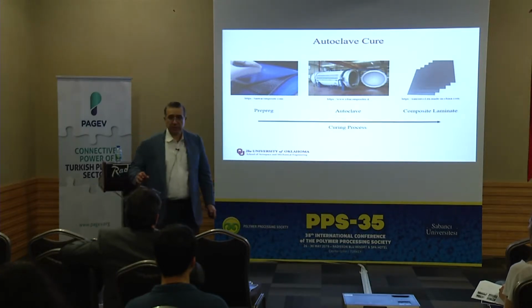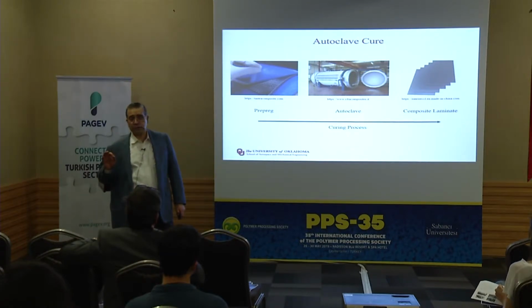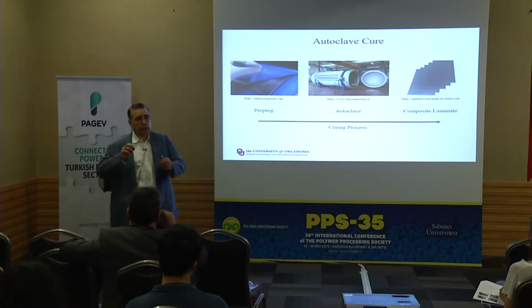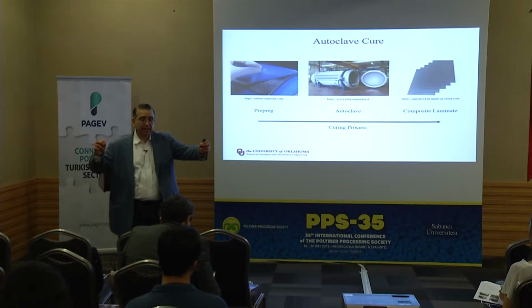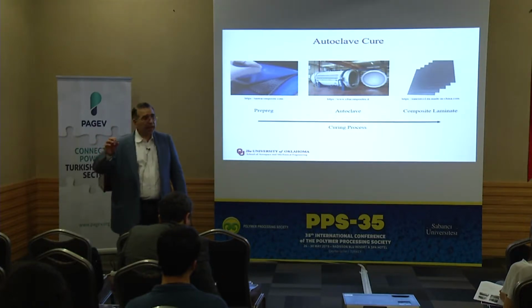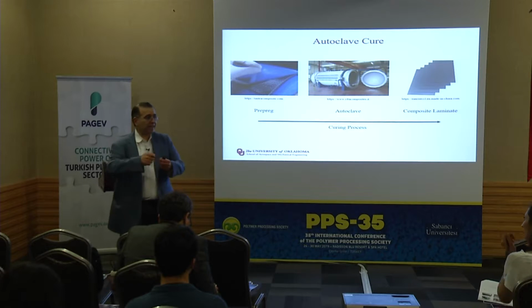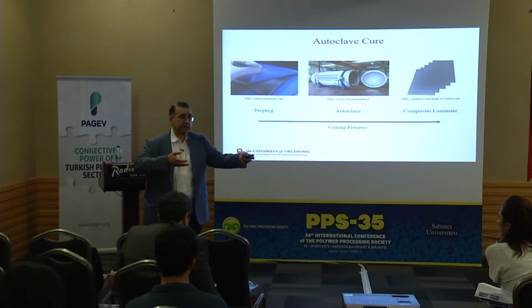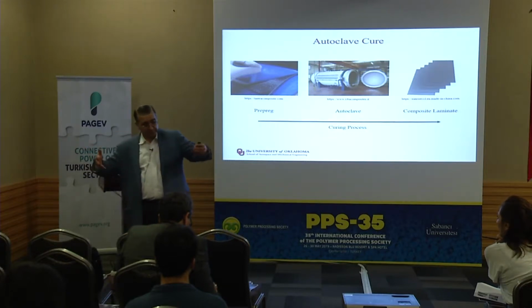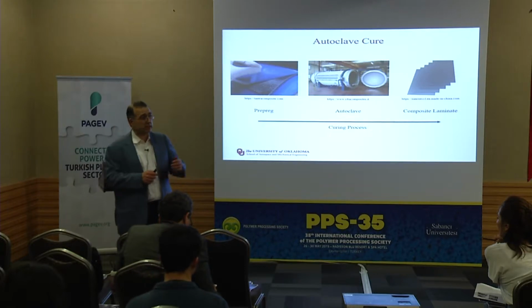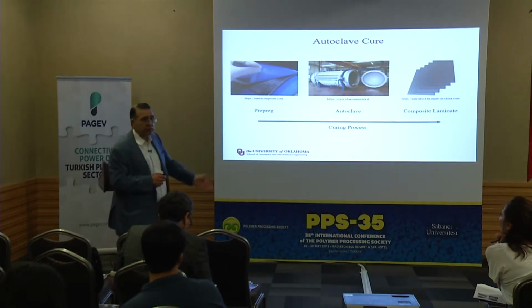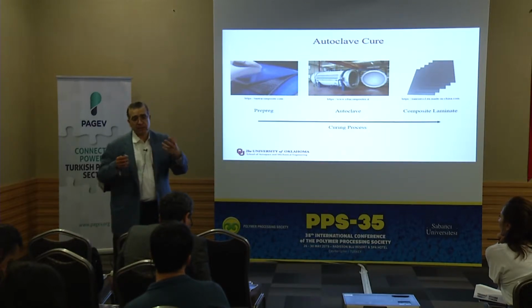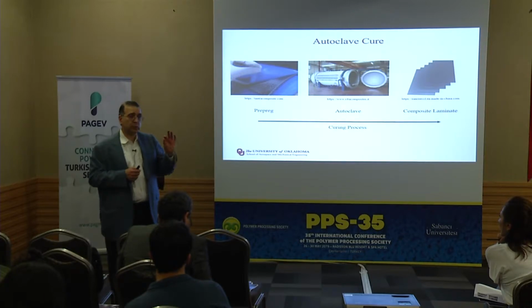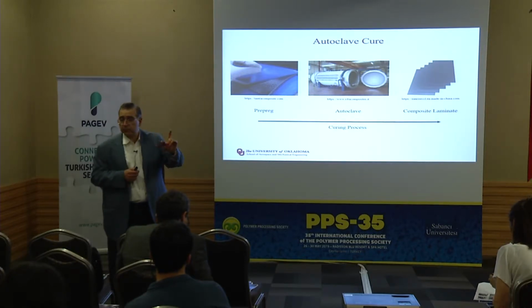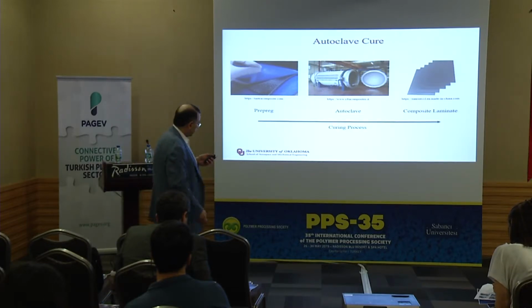If you are working with a prepreg, make sure that you know its shelf life. You make sure that you store it in a sealed bag, in a refrigerator, in as dry an environment as possible. Because as you open and close the bag, if you take it out, there will be moisture. So wherever you are processing this, try to reduce the moisture, because the resin will absorb moisture, and when you are curing, if you do not vent or get rid of this moisture properly, you will have defects. You will have voids that will reduce the properties by 10, 20, or 30%. Okay? So this is our raw material.